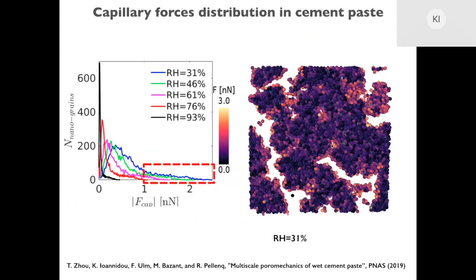Also, on the left, you see the distribution of capillary forces for different relative humidities. And the interesting thing is that at low relative humidities, we have this long tail of capillary forces, which are the highest capillary forces that are seen. And if you notice, the values go up to 2.5 nanonewton, which is good news because it's much smaller than the particle-particle interactions, the CSH-CSH interaction, which is around 10 nanonewtons. So we are safe. As we know, water is not destroying cement.